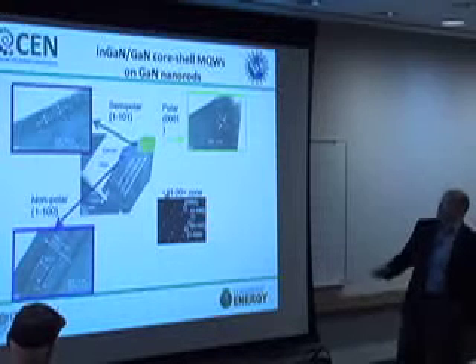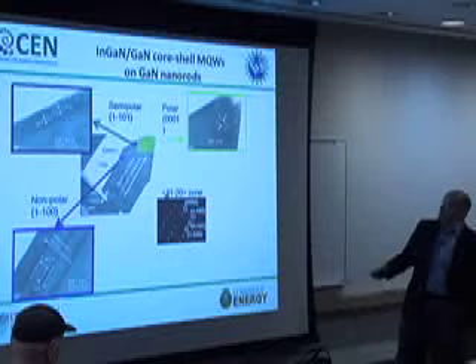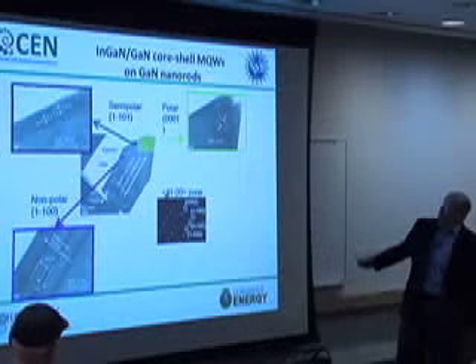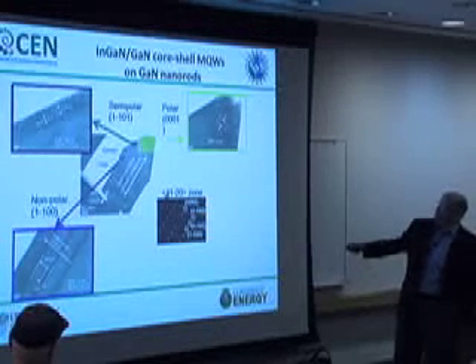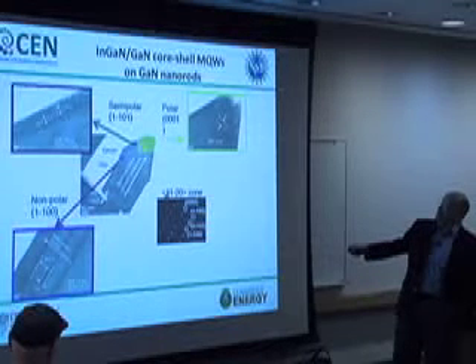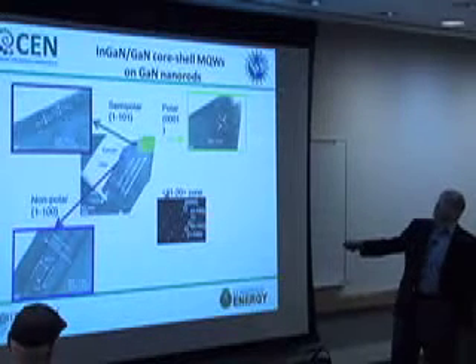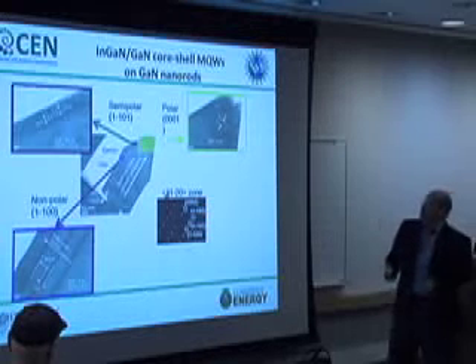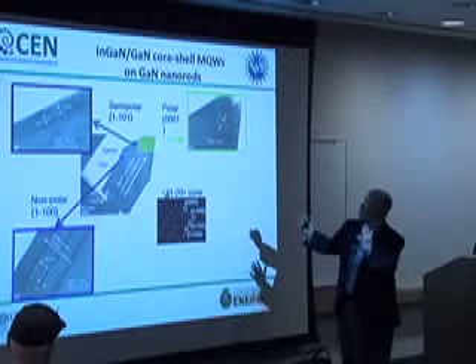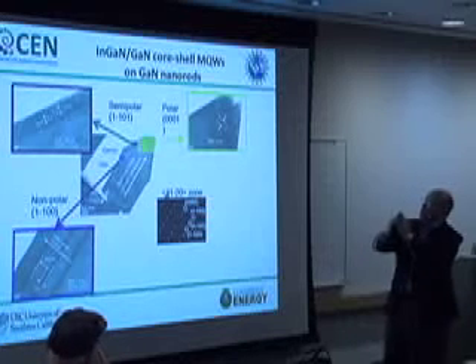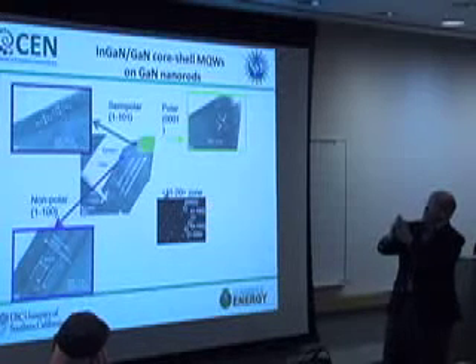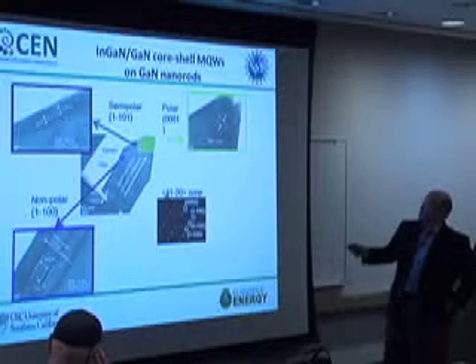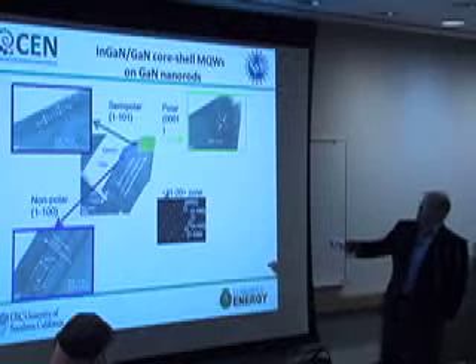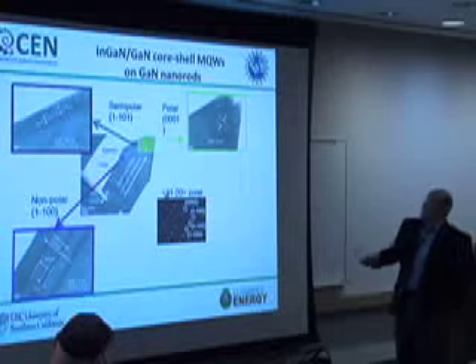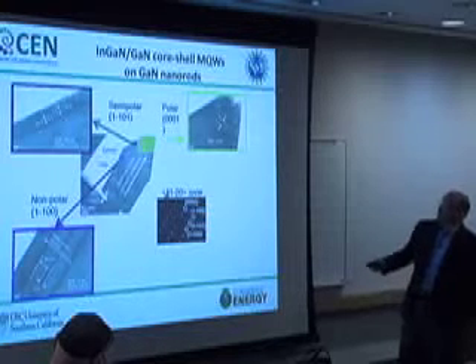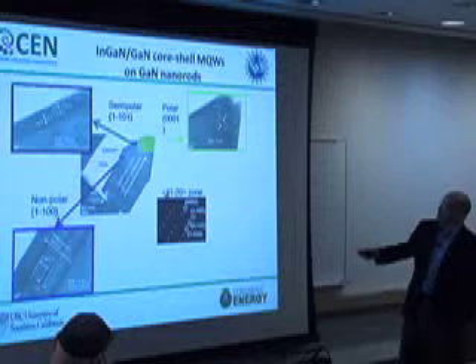So when we have all of these facets available, we'll grow the desired quantum wells on the side wall. We'll grow very thin quantum wells over here, and actually pretty thick quantum wells over here. So we've devised ways of growing under conditions where we pinch off the C-plane, so there's no C-plane when we grow the quantum wells. And under those circumstances, we haven't been able to measure any quantum wells up at the tip of the structure, and we have only the ones that grow here and small ones that grow here.